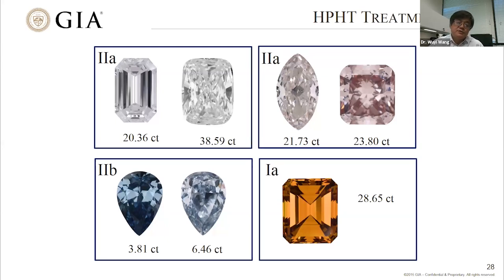Most HPHT treated stones we detected in the GIA laboratory are type 2 diamonds, but occasionally we also see some type 1A diamond treated. For example, here, this is a type 1A, it's over 28 carats after being treated.